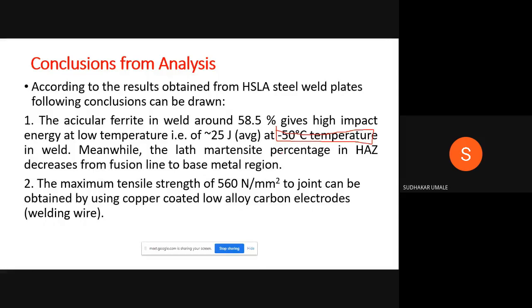I observed that whatever carbides are available after welding can be converted into acicular ferrite by the heat treatment process. So after welding, what is the advanced technology to improve the mechanical properties? That is called cryogenic heat treatment. When you keep the welded material at a cryogenic temperature, that is minus 50 degrees centigrade, for some time, lath martensite is obtained. Sometimes martensite is available in the welded zone as well as the heat affected zone, and that can be converted into acicular ferrite by cryogenic heat treatment, and hence we get the maximum strength.